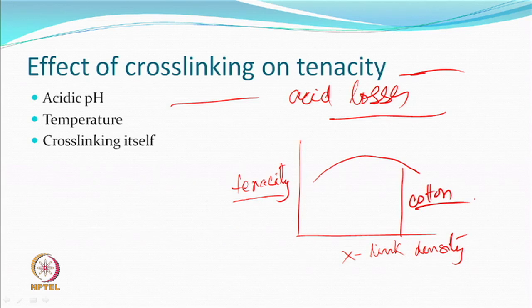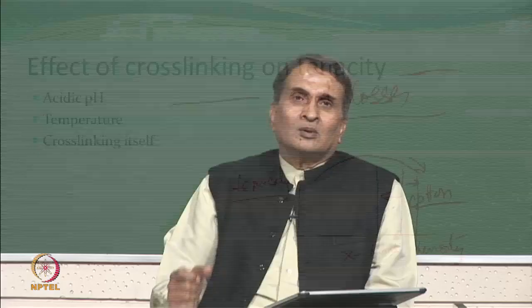So, when you increase cross-link, you are going in this direction. So, you will lose strength just because of this. Its reverse happens when you decrease. When you decrease, let us say by wetting, hydrogen bonds reduce. This cross-link is not only chemical cross-link, it is representing everything, intermolecular, all kinds of bondings. So the strength increases, so we see the cotton strength in wet state is higher than the dry state. So this is one.